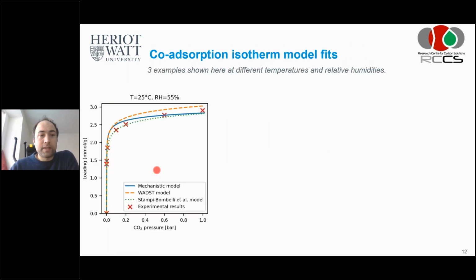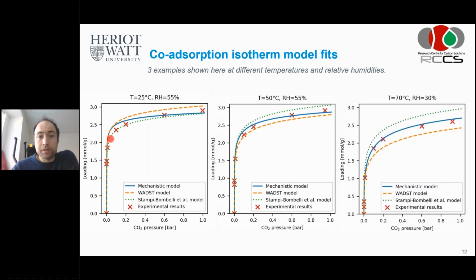And we'll show you the results again. First we come to the isotherms. We show you here different examples at different temperatures and relative humidities. This one is for 25C and for a relative humidity of 55%. What you see here is the partial pressure, and here you see the CO2 loading. This is very simply an isotherm of CO2. The red crosses are the experimental results, and the lines are the different models. We have in blue the mechanistic model, in dashed orange the weighted average dual site Toth model, and in the green dotted line the Stampi-Bombelli et al. model.